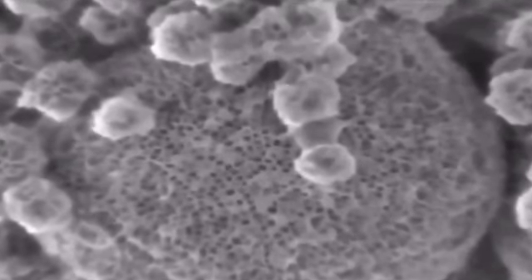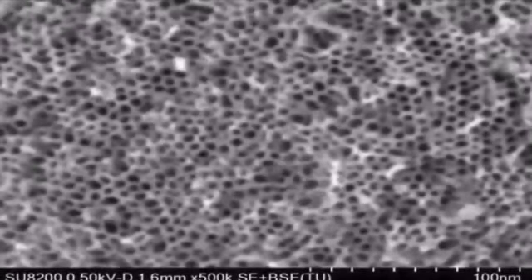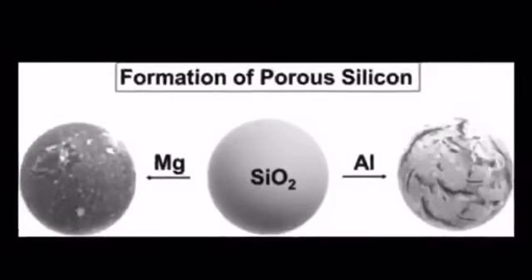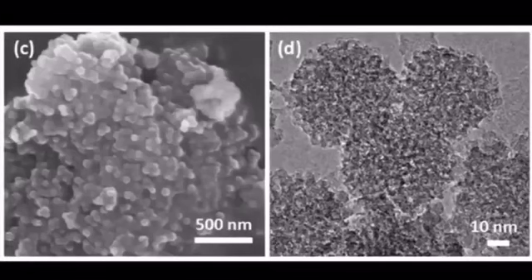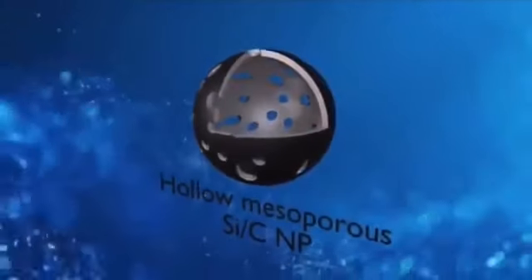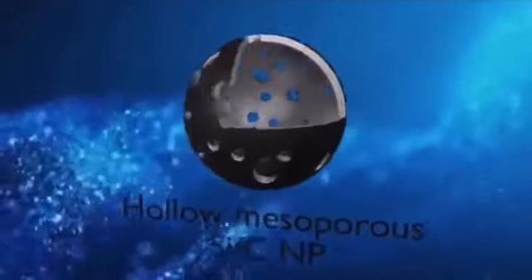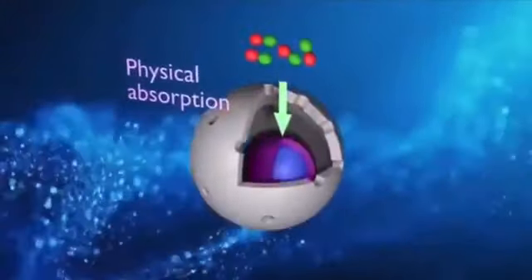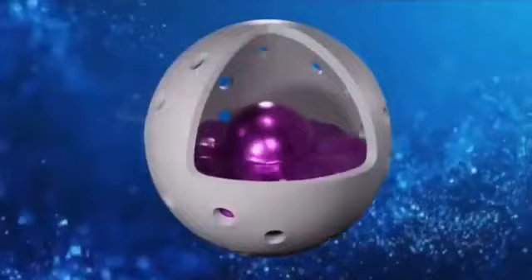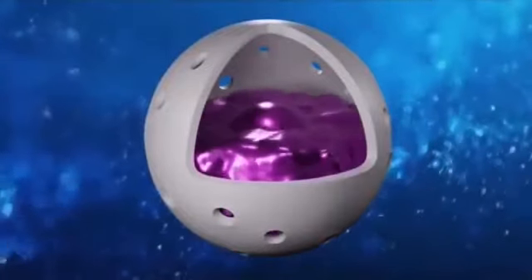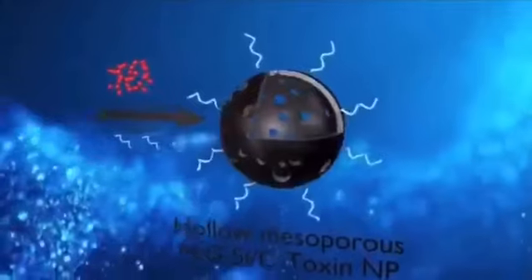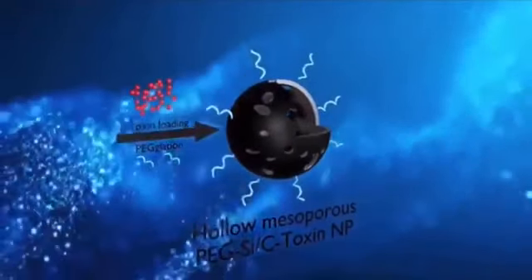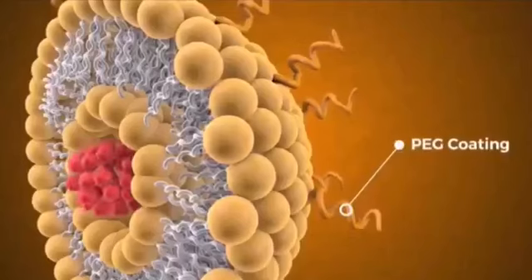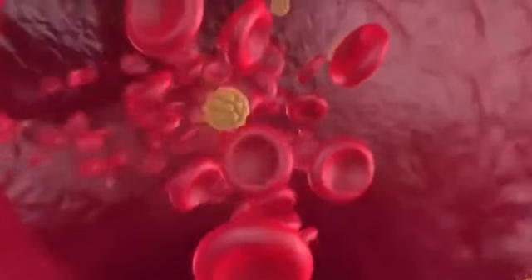After cooling, the sample is stirred in a hydrochloric acid solution to remove the magnesia and create a porous structure in the carbon shell. To create the hollow core center of the nanocapsule itself, the silicon dioxide inside is then removed using a hydrofluoric acid solution. Now the resulting nanocapsules are ready to be loaded to a high capacity with toxins. This process is facilitated by an electrostatic attraction between the nanocapsule and the toxins, due to different voltage potentials. The final step is to give them a bio-stealthy coating like PEG, in order to prevent the body from recognizing and rejecting them.